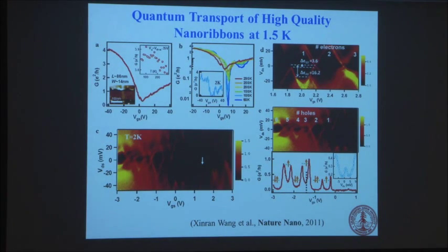And my own group did some electrical measurements all the way down to about 2 Kelvin, of an individual ribbon. And we can see single electron charging, Coulomb blockade. And we can look at some of these excited states. So these parallel lines are these excited states along, confined by the length of the ribbon.